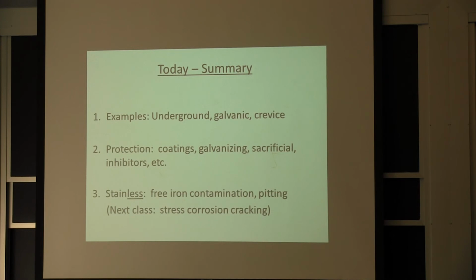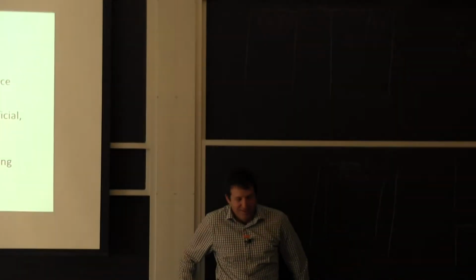So I hope that you get the idea that a lot of different corrosion processes will take place. There are ways to control them. It's very hard to completely avoid the reaction of the metal with the environment. It wants to go back to where it was, but you can control that reaction. So the coatings essentially defer the penetration of moisture and oxygen. Galvanizing is using a sacrificial material, or a current for permanent anodes. The inhibitors are applicable for closed systems. And I think for stainless steel, you have some idea: manipulating it and adding regular steel to it is a problem. Pitting is a problem. It typically comes with chlorides and either surface finish, or just chlorides, or chlorides and temperature, depending on what the situation is. So I had to rush a little bit at the end. I'm sorry. That's what I had today. Any questions?